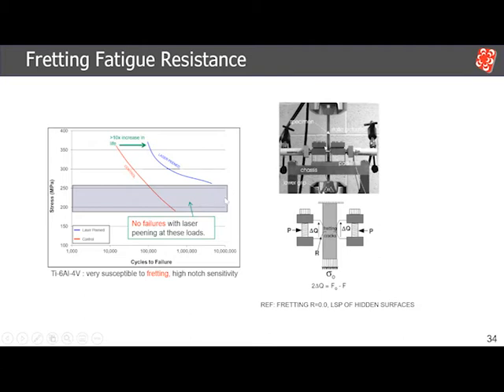The reasoning here is below a specific stress, the compressive stresses that you're generating can fully protect the material from a crack initiation in the first place, giving the part almost a full life without failures up to the testing endurance limit.